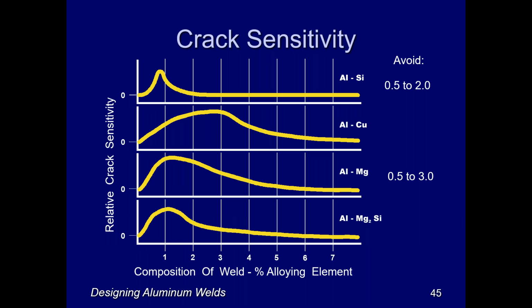Now, I mentioned crack sensitivity, and if you want to put a little finer point on it, the composition of the weld metal after the weld is made, mixing the base metal and the filler metal, will dictate whether or not you're in the crack sensitive zone based on a certain composition of the alloying element. So for example, if you've got silicon in your base metal and filler metal, you want to avoid silicon content in the weld metal of between 0.5% and 2%. That's where the crack sensitivity is the worst.